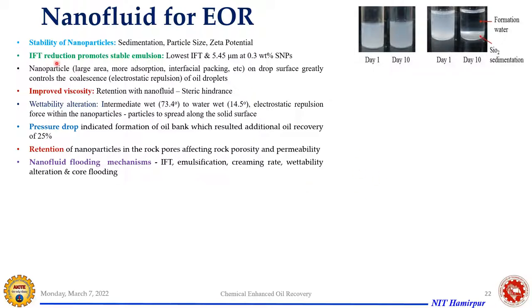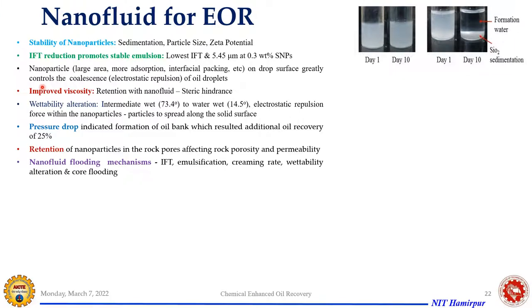Once it is done, in the same pattern we have studied the IFT. We have seen lowest IFT and lowest droplet size of 5.45 microns at 0.3 weight percent nanoparticles in this case. And as I have told you, these nanoparticles have large surface area, so they could accumulate more chemicals on their surface. So there will be better interfacial packing at the interface, and several other properties form a very rigid, stable film at the interface, which is quite effective compared to only chemical flooding. This greatly controls the coalescence, because of this electrostatic repulsion, nanoparticles are suspended and will not coagulate and form a bigger drop and settle at the bottom.